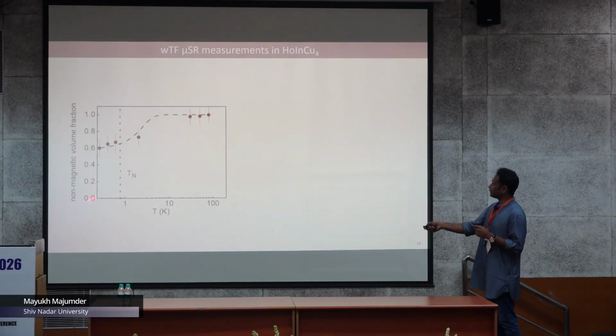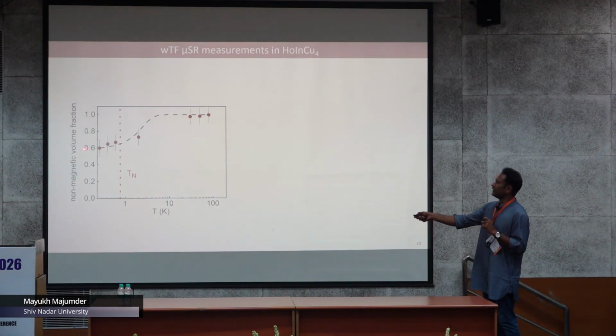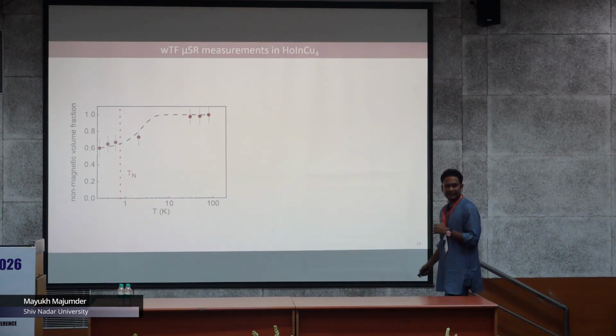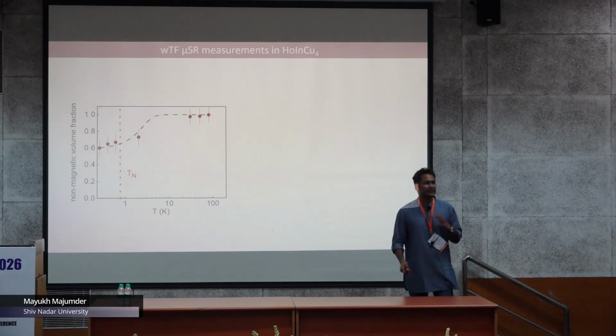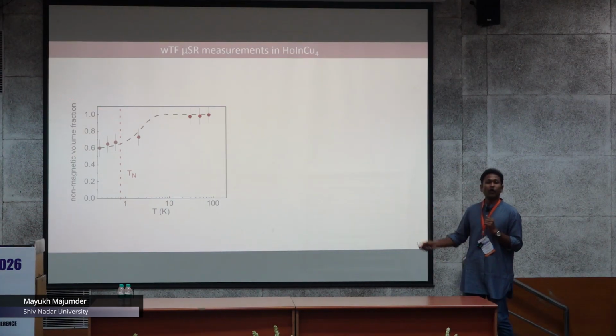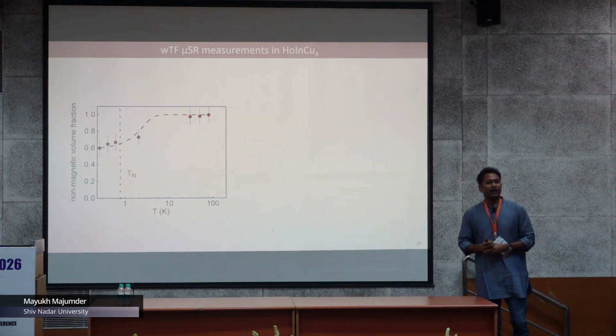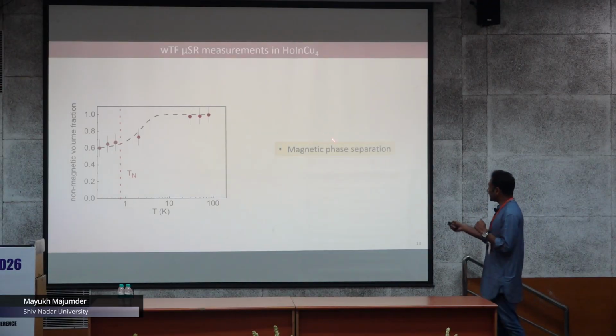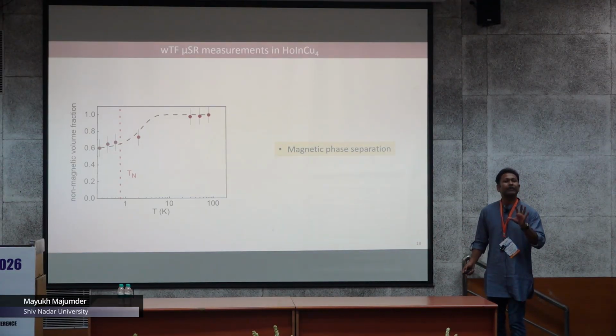Okay, fine. So I am going to talk now about the results, the weak transverse field results, on the compound on which we worked. So first, the weak transverse field result, as I told, gives you information about the non-magnetic volume fraction. So you can see below the phase transition temperature Tn, it does not show 0, but rather, let's say, stuck at 0.6, indicating that 60% of the spins are still dynamic, whereas the rest 40% probably shows some sort of static type of correlation. So it indicates directly that you have some sort of magnetic phase separation.